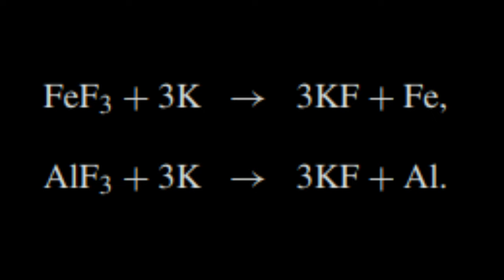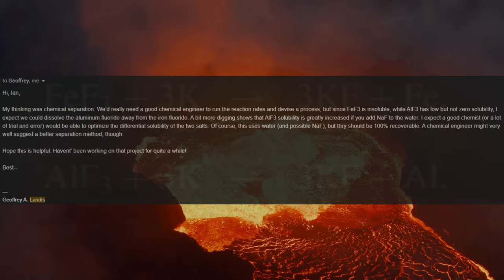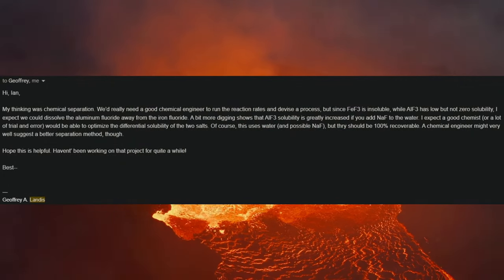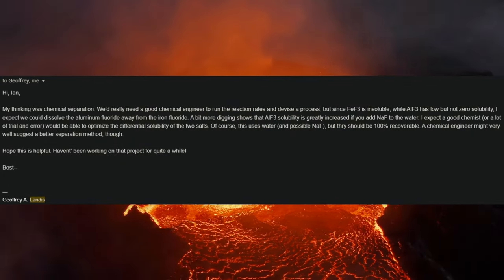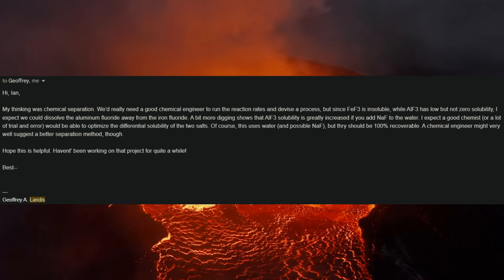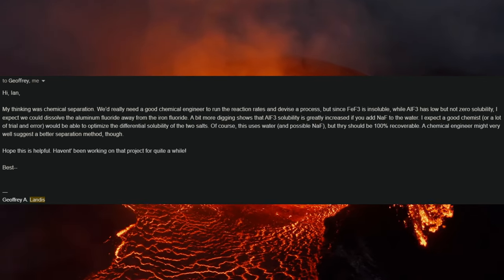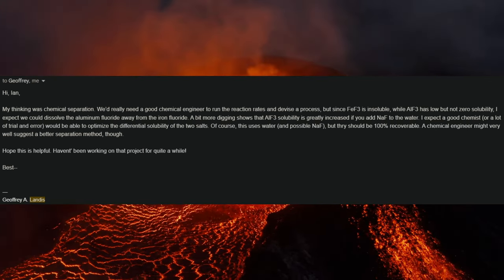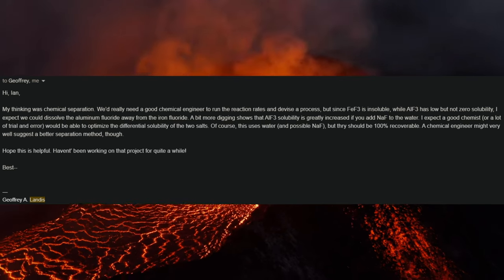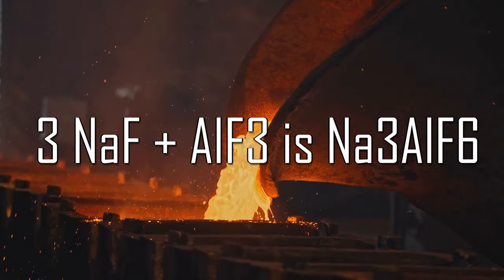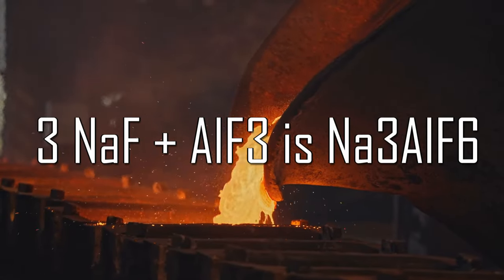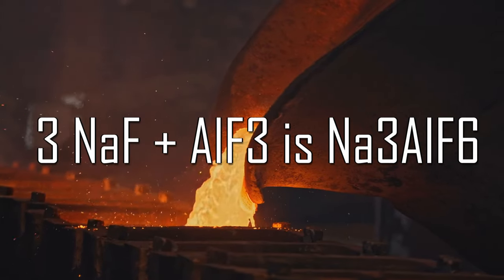I was at a loss of how to separate these, so I reached out to the big man himself, and he suggested we should be able to use molten sodium fluoride, the same stuff we'd be using to reclaim our fluoride and potassium, directly on the alloy cake, since aluminum fluoride is very soluble in it, but iron fluoride is not. This would actually create cryolite, which could then be electrolyzed to produce pure aluminum and fluoride.